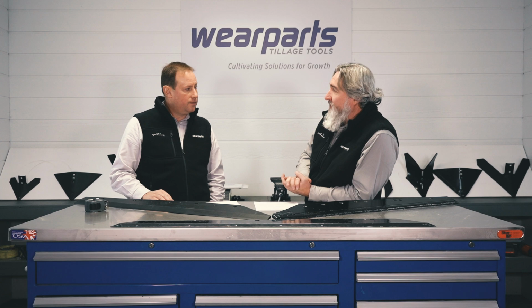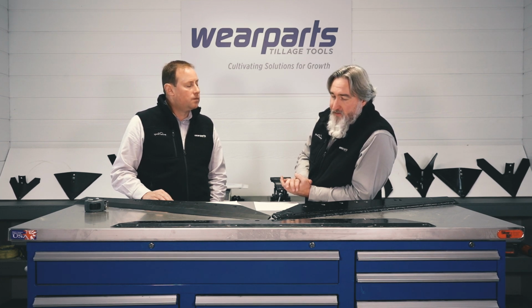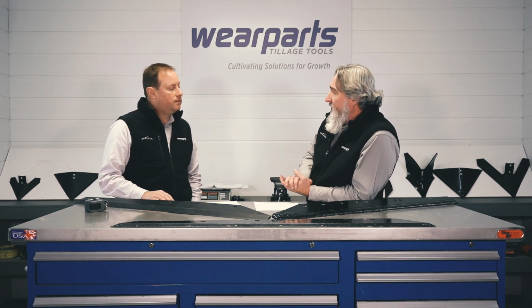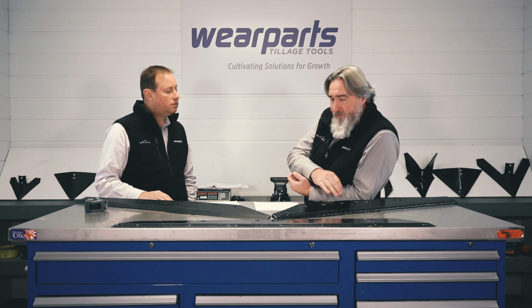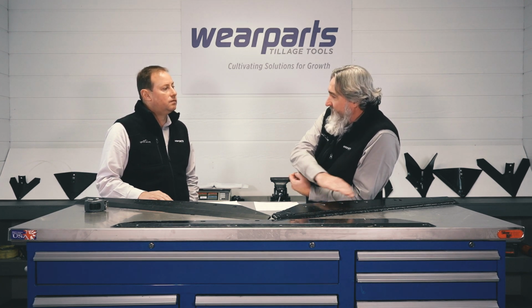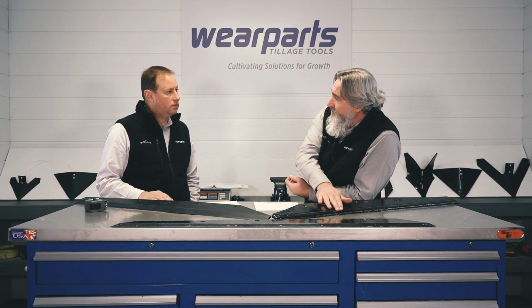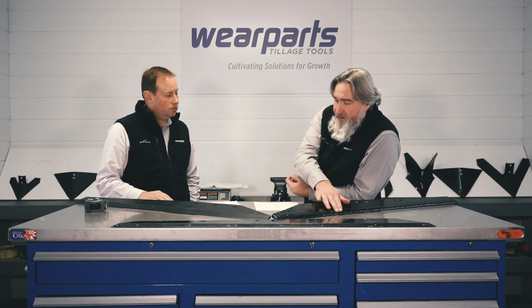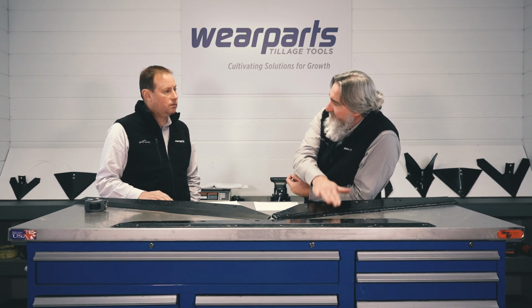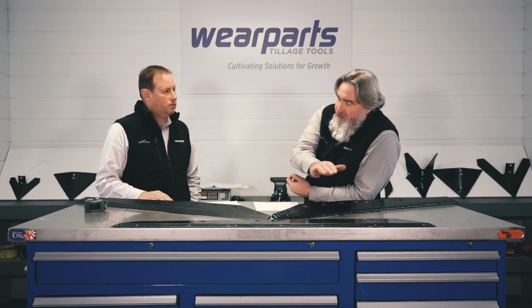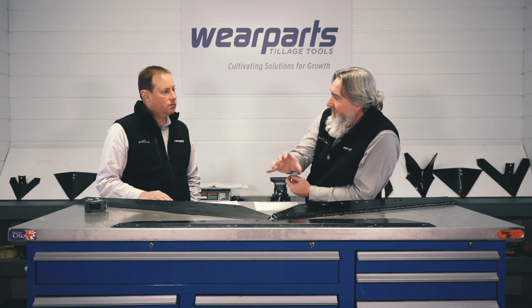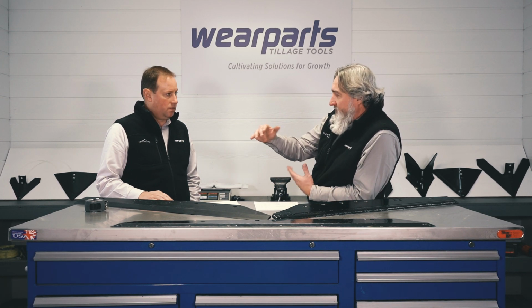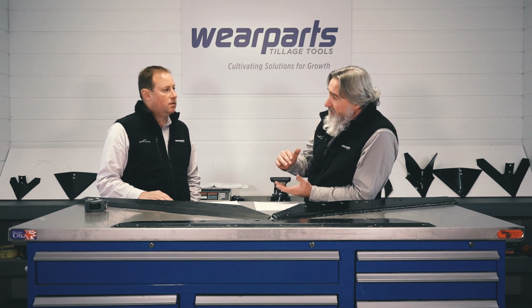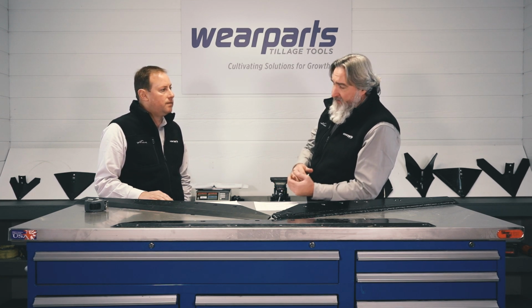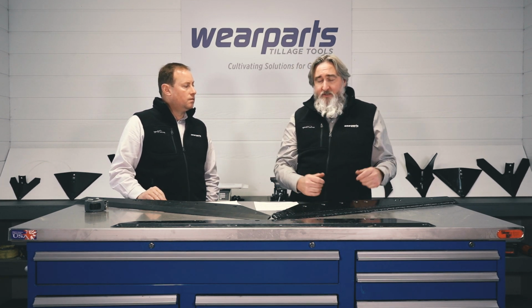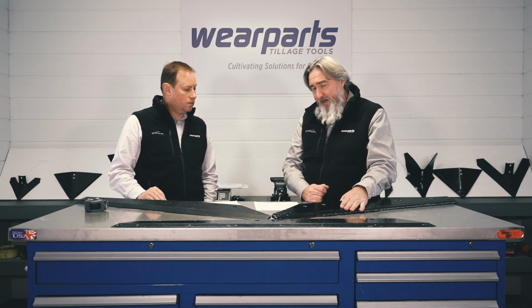So the way that we tackle that problem is with our cold metal transfer. The cold metal transfer is a lower heat input, so you're not putting as much heat into the blade, and you're not going to get warping over the length of that blade. You're also not going to get dilution of the material, so that hard metal is going to stay on top. It's not going to be sinking down into the base material. You're going to have reduced cracking because you don't have that extreme temperature difference between the base material and the hard facing that you're adding onto it. Right, having that difference and that cooling can cause cracking, so that helps avoid that.